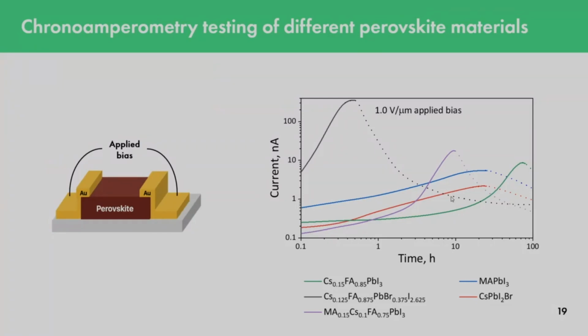But after some point, the concentration of these defects becomes so high that they don't work as dopants anymore. They start the degradation process itself, and then the current starts decreasing. So in this situation, it's probably correct to assume that if we measure the area beneath the part where the current is increasing, we will be able to at least make an assumption which material can sustain the most amount of these defects accumulating inside of it.